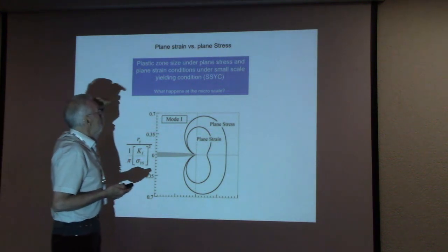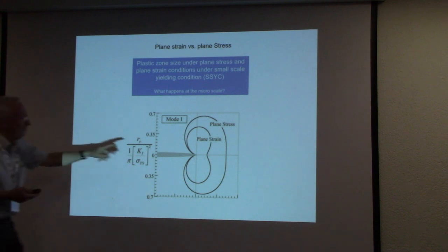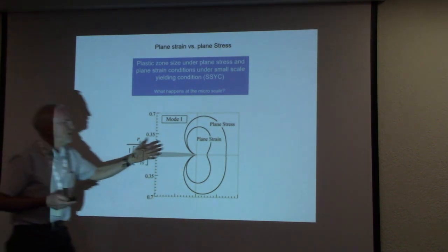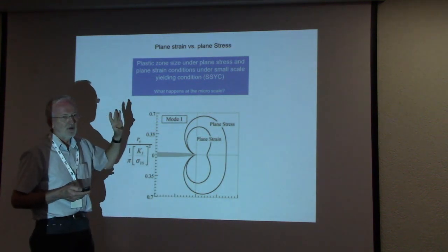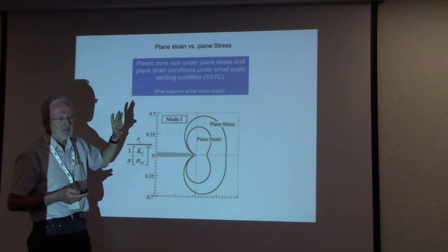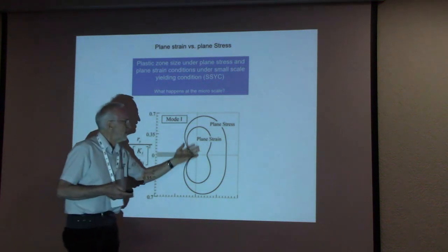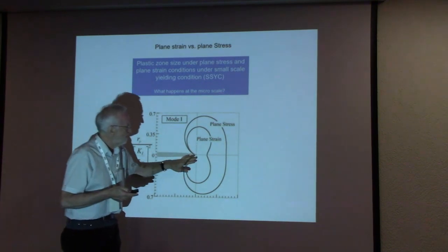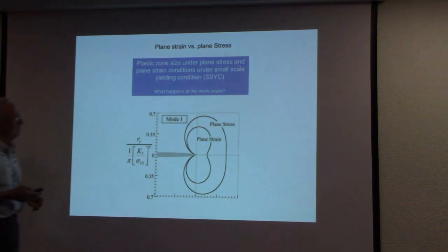Then we always ask, what is the stress state at the crack tip? And what is the stress state at larger distance in the plastic zone? This is also important when you go to the semi-brittle process, yes? Because semi-brittle fracture may occur in the whole nonlinear region, whereas ductile fracture mainly occurs at the crack tip.